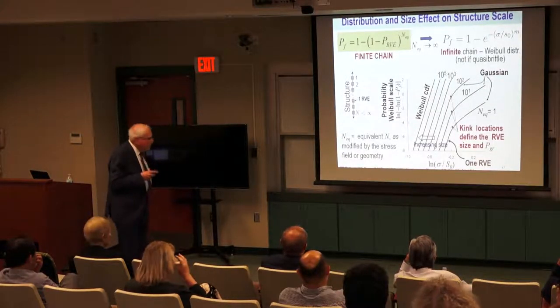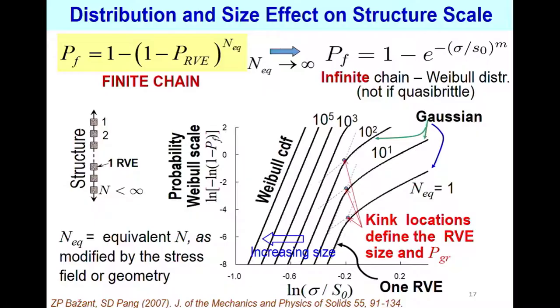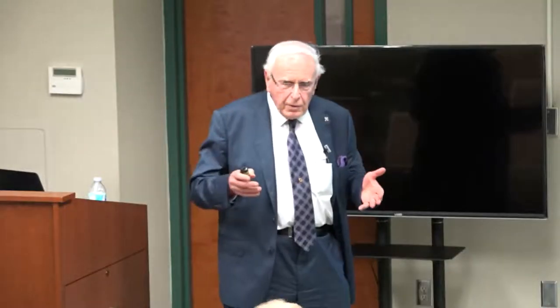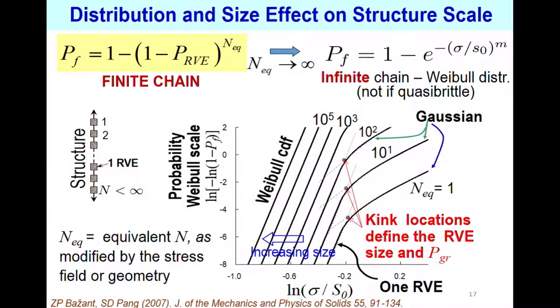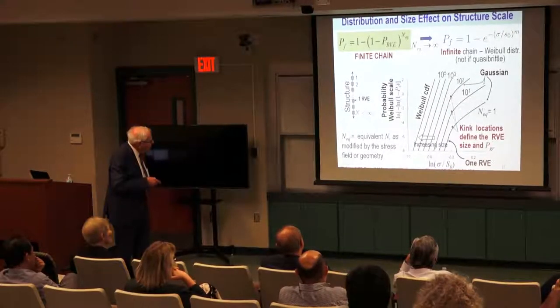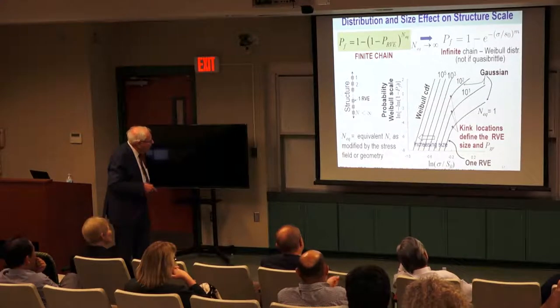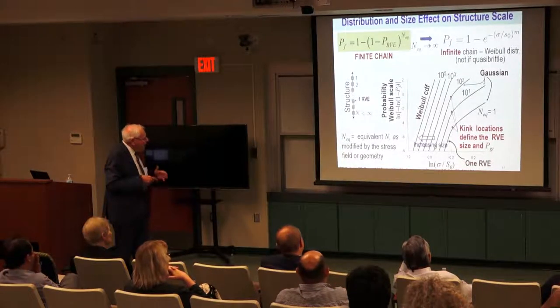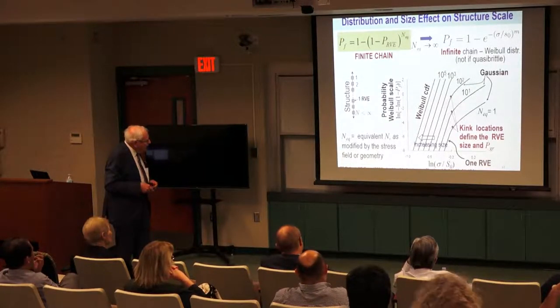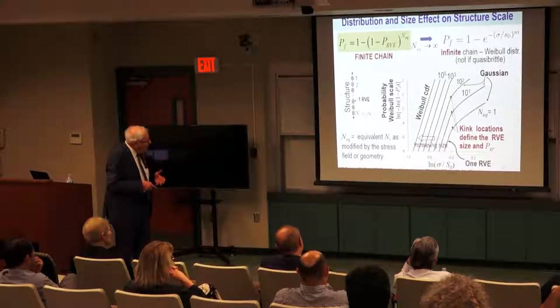So the result of these calculations, I am leaving out what is in a number of papers over the last 10 years, is that we plot the distribution on Weibull scale. Now, you know the normal probability paper, right? The normal distribution appears as a straight line. So also on Weibull paper, the Weibull distribution in that scale gives a straight line. This is a transformation of the probability of failure. And this is the size on the logarithmic scale. This is the Weibull distribution. And now we get it for one representative volume element, one curve.